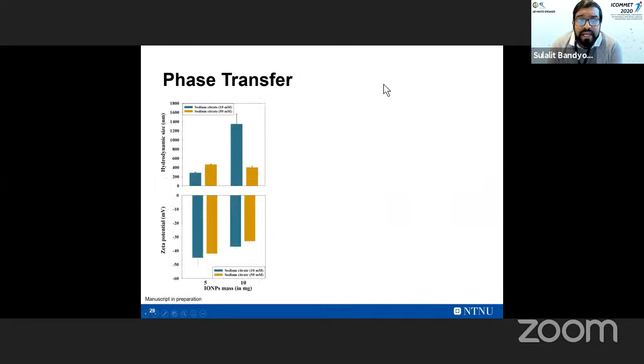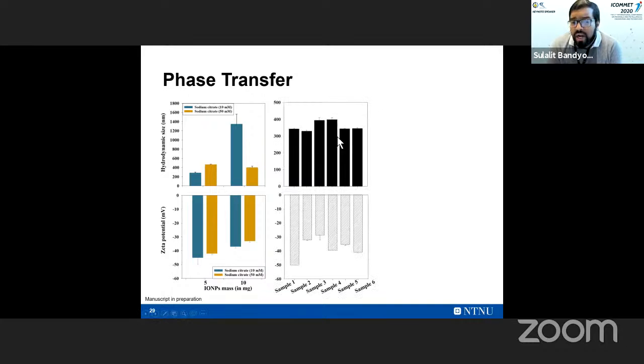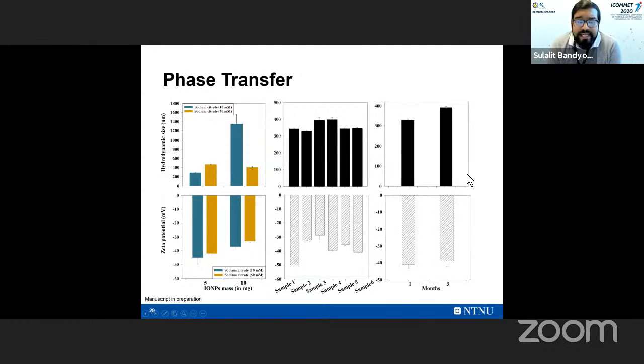So with that, I would show you the final data regarding functionalization, where this is for the iron oxide nanoparticles. And as you can see, they are quite repeatable with a size range of 350 nanometers and good zeta potential. And also they are quite stable over several months. So this means that I have now given you a brief overview of how we tailor nanoparticles in order to control their shape, size, and morphology.